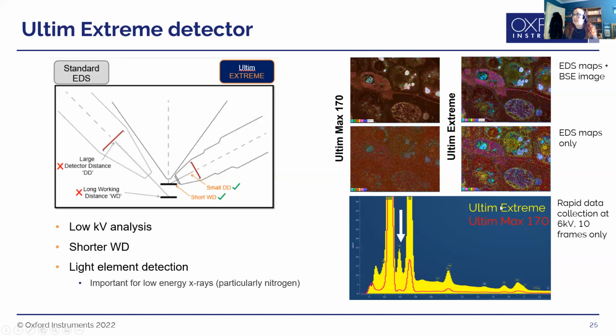So here we've got a comparison, Ultim Extreme, and our largest normal or standard EDS detector. It's a bit unfair on the Ultim Max because we're only at 6 kV here. But hopefully you can see this nitrogen peak that I've indicated with the arrow. It's really clear in the Ultim Extreme data and less clear in the Ultim Max 170. And you can see that in the maps. We've got nitrogen coloured in yellow here.